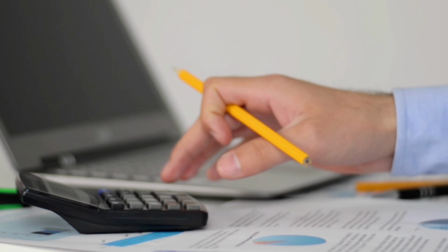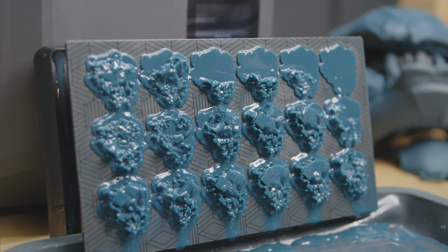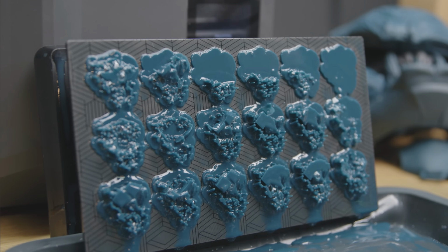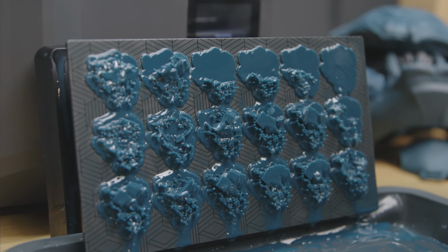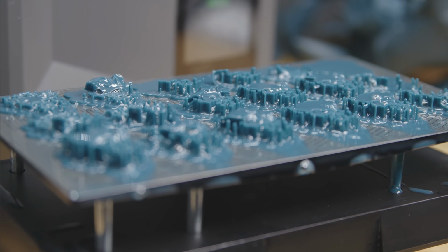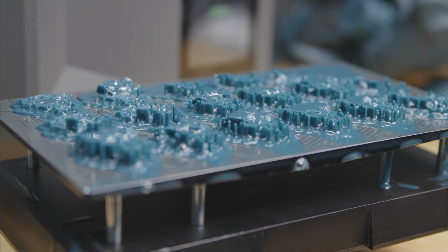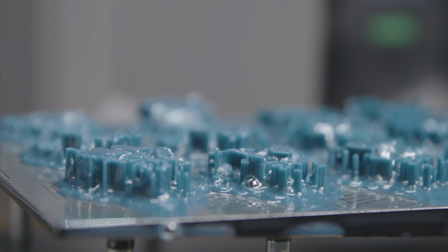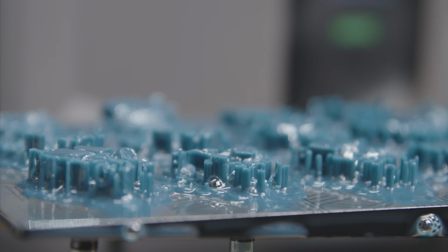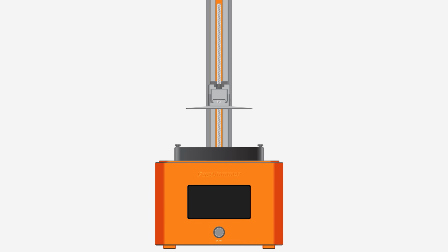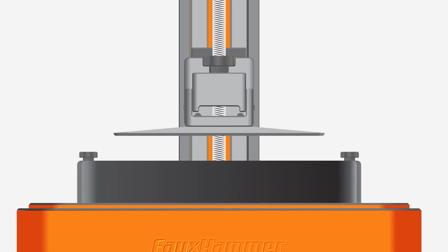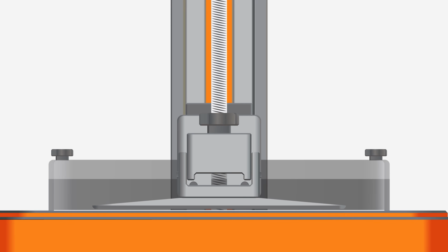But when should you change this? Well, if you're getting prints where the base and maybe some of the supports begin to print, but then suddenly everything is torn away and stuck to the release film, increasing your transition layers could help. However, there are times where it may not be that. It may in fact be due to your wait times or lack thereof, or it could be due to your lift speeds, which I'll come on to shortly.